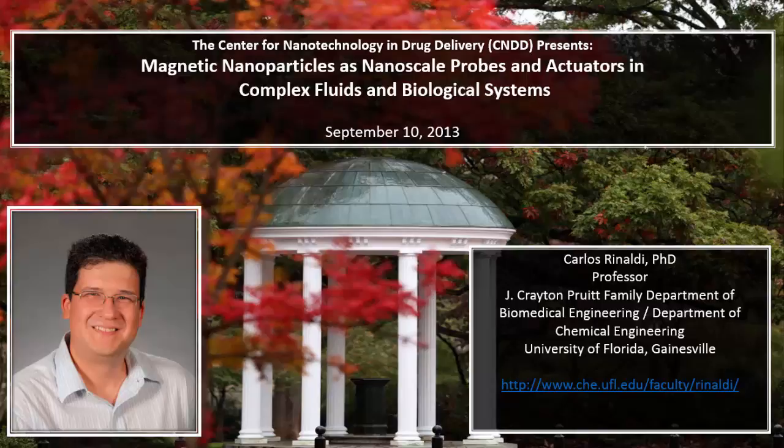So we make our particles. I'm not going to show you the details. And then the question is, does the targeting make a difference in terms of uptake of the particles by cells? We incubate the cells with particles, then we wash, we remove all of the unbound particles, we digest the cells using nitric acid, and we measure iron concentration using ICP-MS.